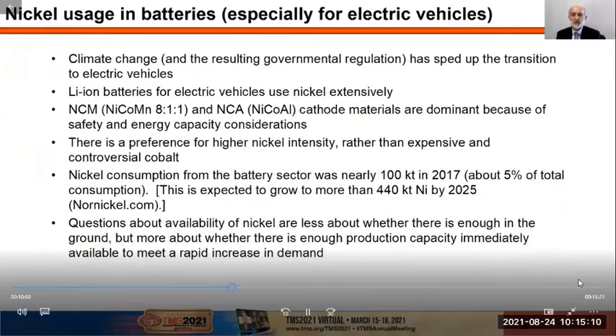Climate change and the resulting governmental regulation has sped up the transition to electric vehicles, and lithium-ion batteries for these vehicles use nickel extensively. The NCM batteries, that's nickel, cobalt, manganese, most commonly in an 8:1:1 ratio, and the NCA, or nickel, cobalt, aluminium cathode materials, are dominant because of safety and energy capacity considerations. There is a strong preference for higher nickel intensity rather than the expensive and rather controversial cobalt.